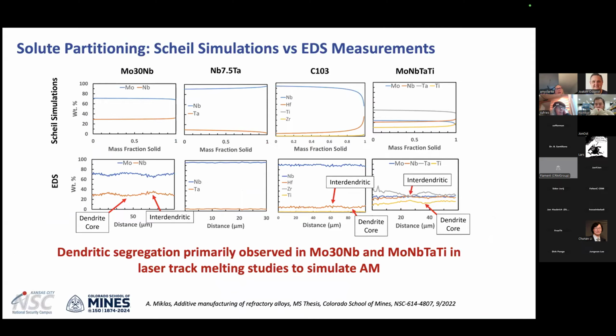We do know when we take all these different high melting point elements and put them together and alloy them together, that we do expect things like microsegregation during solidification. This is early melt track work that my student Abby did, looking at Scheil simulations as compared to EDS measurements for some binary alloys as compared to C103, and then a quaternary refractory multi-principal element alloy. And again, we tend to see differences in the interdendritic regions as compared to the dendrite cores.